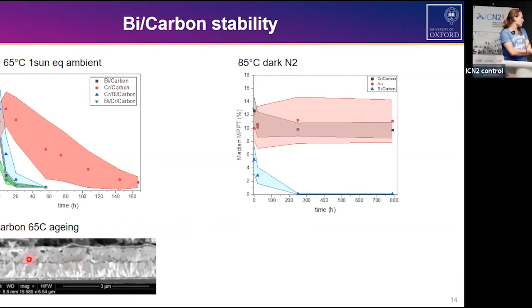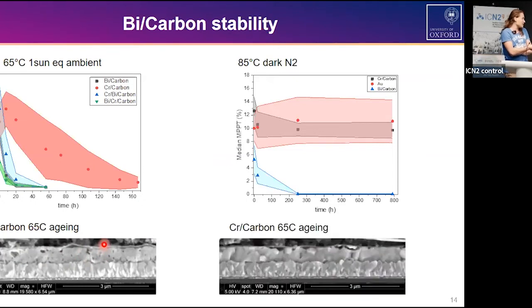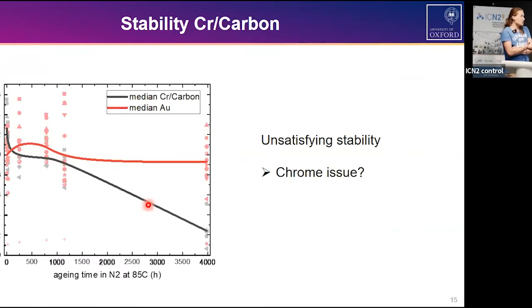So there was consistently no grain boundaries, but lots of holes in them. And it's not beam damage, because the same devices with a chrome layer look like this. We see also holes, but we see a lot of grain boundaries in it. So it's really strange behavior of the aging. And the chrome was still, but in the stability study, we see that chrome carbon is also not delivering the promise it had on stability. We don't know yet why.